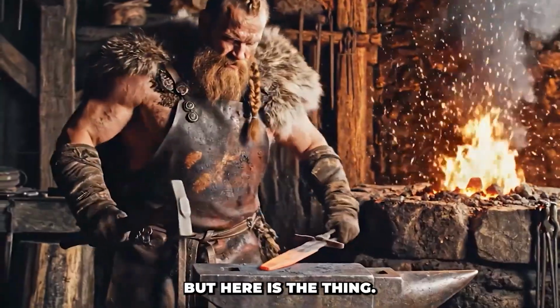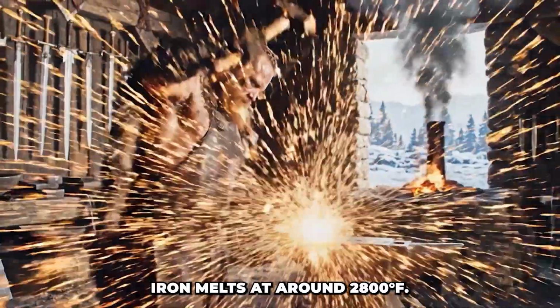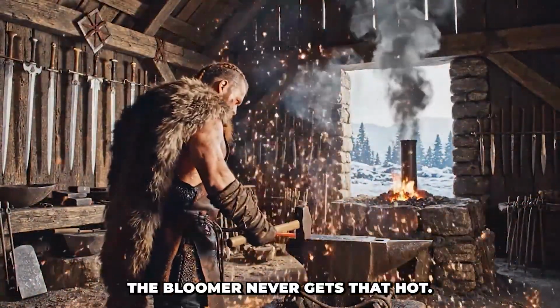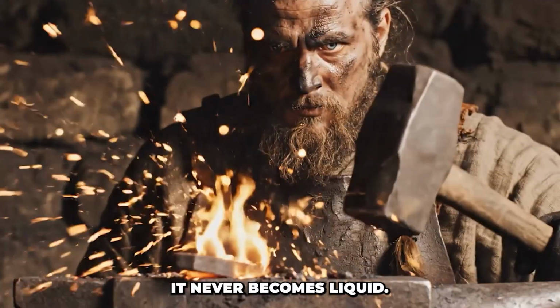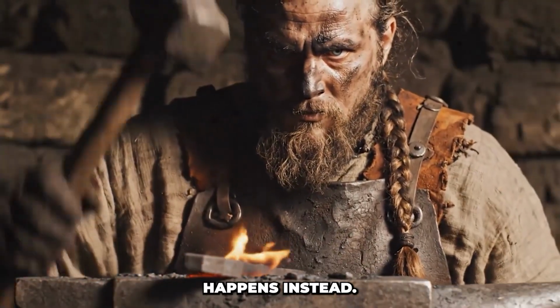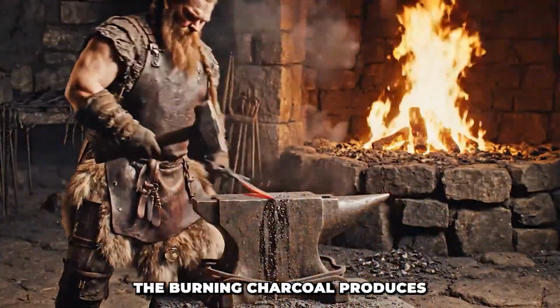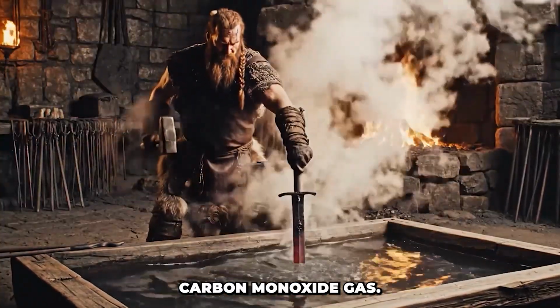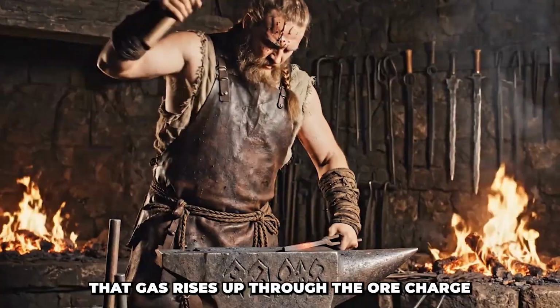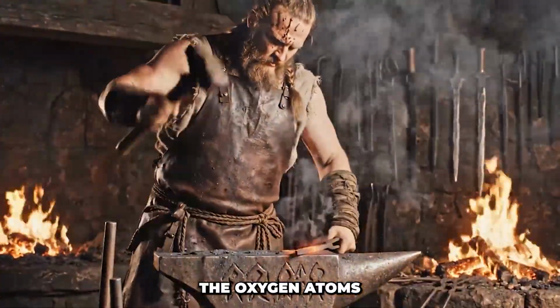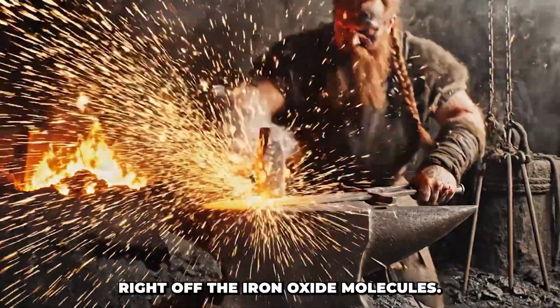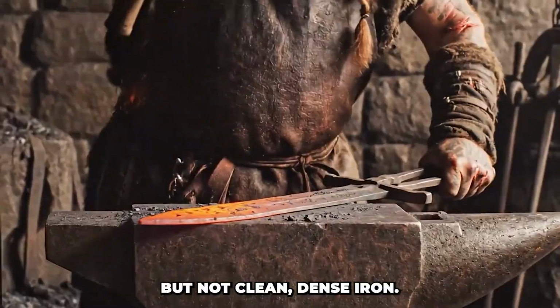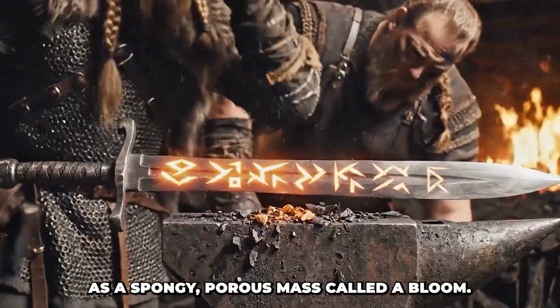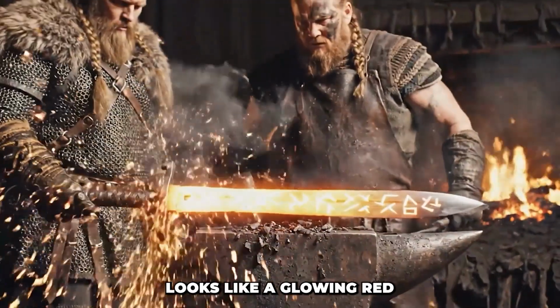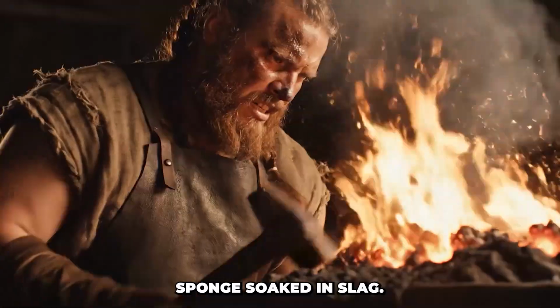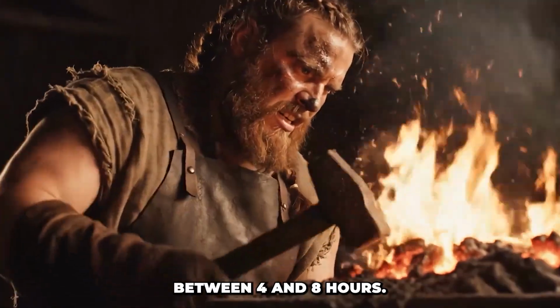But here is the thing. Iron melts at around 2,800 degrees Fahrenheit. The bloomery never gets that hot. The iron does not melt. It never becomes liquid. Something more interesting happens instead. At those temperatures, the burning charcoal produces carbon monoxide gas. That gas rises up through the ore charge and chemically strips the oxygen atoms right off the iron oxide molecules. What remains is iron, but not clean, dense iron. It collects as a spongy, porous mass called a bloom. Looks like a glowing red sponge soaked in slag. The whole smelt takes somewhere between 4 and 8 hours.